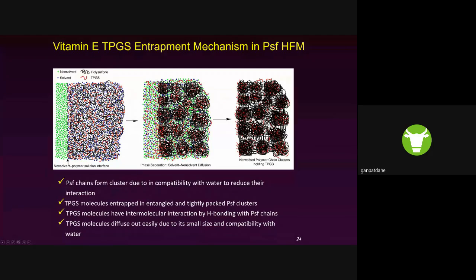When the phase separation happens, some of the TPGS leaches out from the polymer solution, and some of the TPGS gets entrapped in the polysulfone, which is the case in most instances. In this phase separation there is a phenomenon called vitrification. There is a sudden freezing of the structure, and that sudden freezing helps to entrap the TPGS in the polymer matrix.